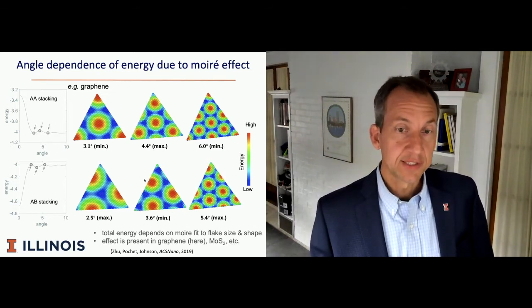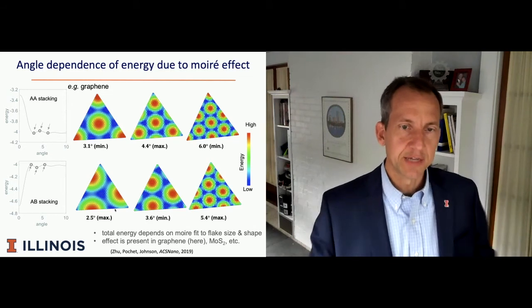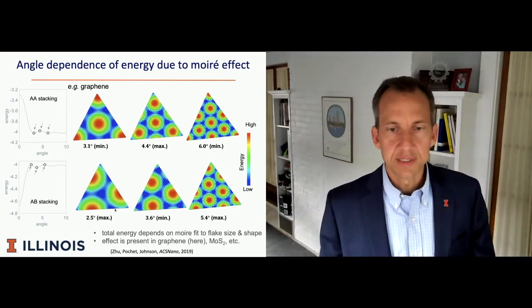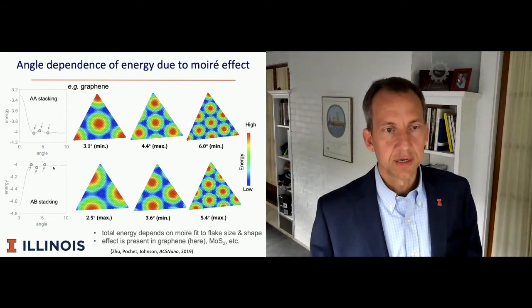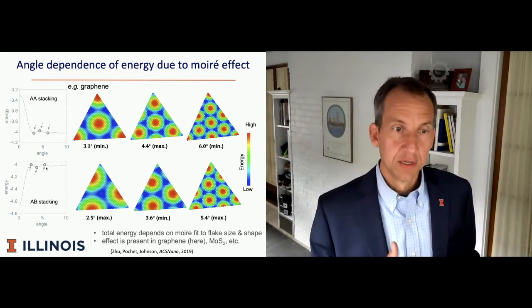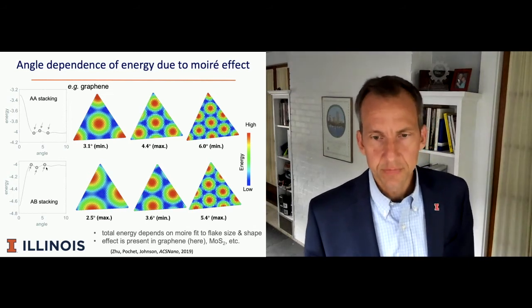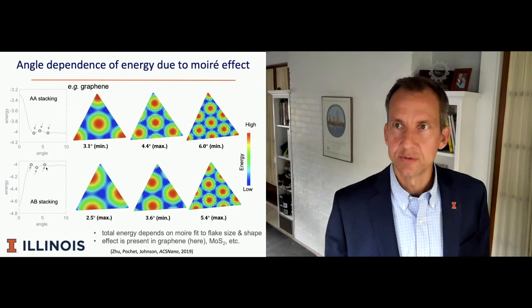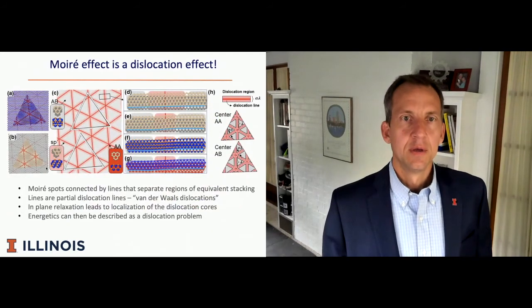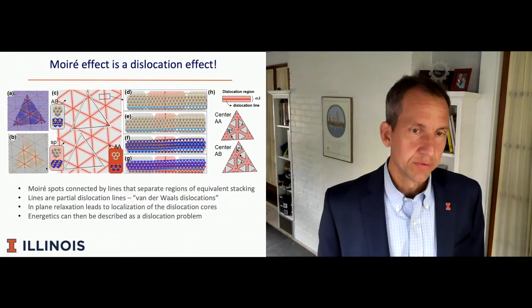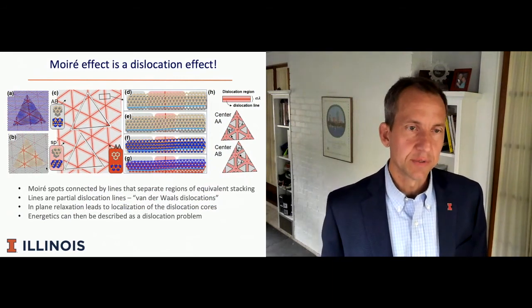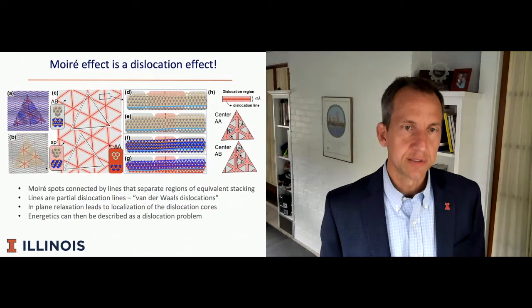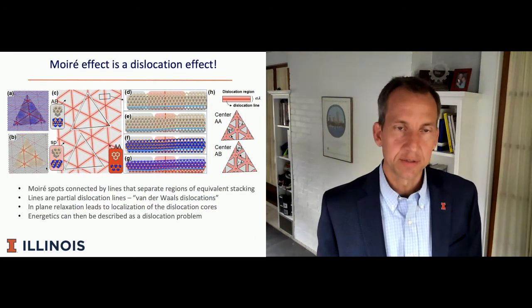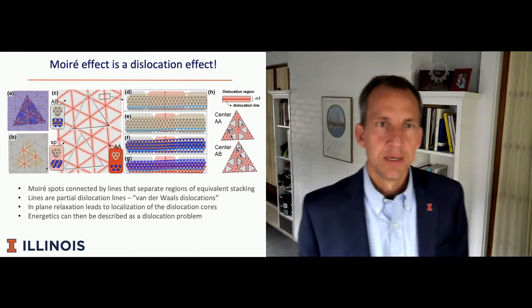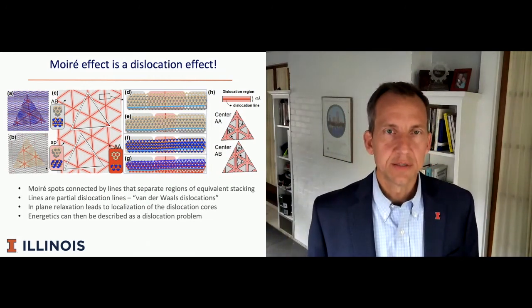It also depends on the flake size. As we imagine growing the flake larger and larger, we see that this energy surface changes, but there are still the features of local minima and local maxima. Again, it's present here in graphene, it's present in MoS2, and so on. What we have concluded through a series of attempts to model this in different ways, both numerically and analytically, and I'll say a little bit more about the models as we go, is that the moire effect necessarily should be understood as a dislocation effect.